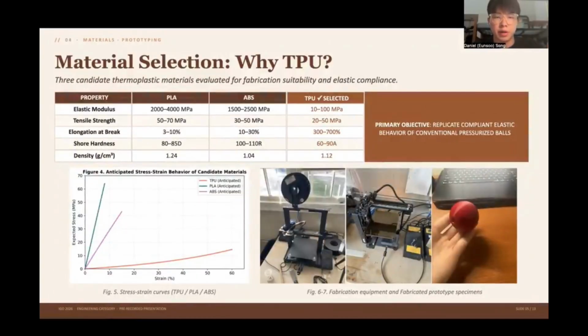TPU's elongation at break, 300 to 700%, dwarfs PLA and ABS by an order of magnitude. That difference in compliance is what allows the lattice shell to compress and rebound like a pressurized ball.